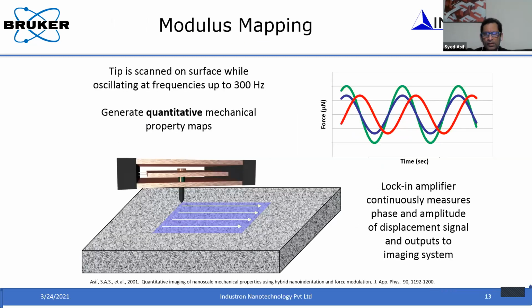Okay. So what I have talked about so far is measuring the property at one location, the same way that you do depth-sensing indentation: you apply a load and measure the displacement at one location. But we can also extend this to a mapping technique, where we scan on the surface while continuously measuring the response. For example, you measure the contact stiffness, the loss part and the storage part, and then scan on the surface the way you do SPM imaging, like in AFM or in our system, in situ SPM imaging. You can measure this mechanical response as a map. Which means that on viscoelastic materials, not only can you measure the properties, but you can also construct a map or an image.